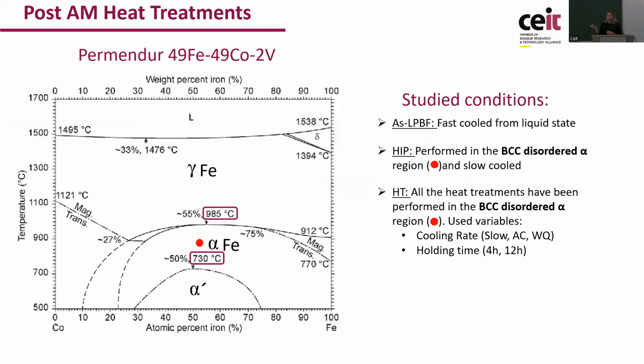So talking about Permendur material, the composition is iron, cobalt, and 2% of vanadium. So we can follow the typical binary phase diagram that you can observe on the screen. The studied conditions were first as laser powder bed fusion, or as SLM material, which is melted by laser and then rapidly cooled. And then the other conditions were after heat treatment, both after HIP, hot isostatic pressing, and also